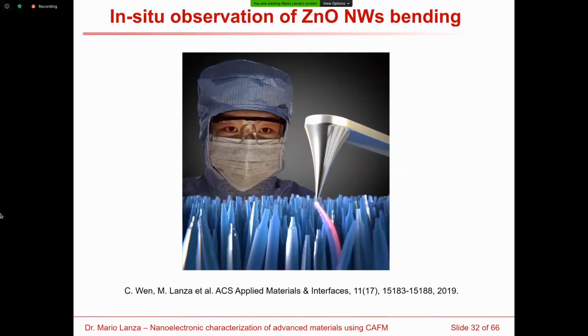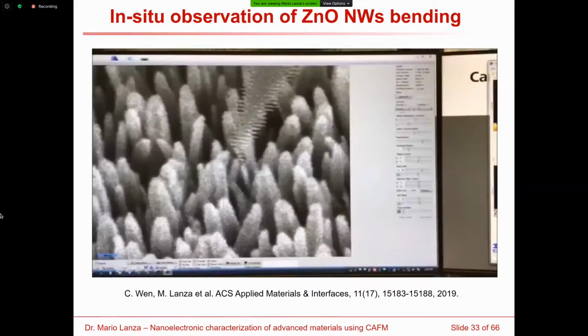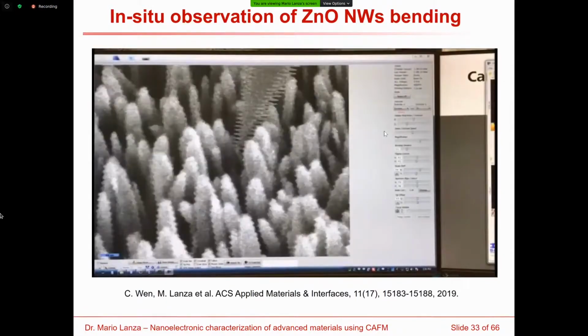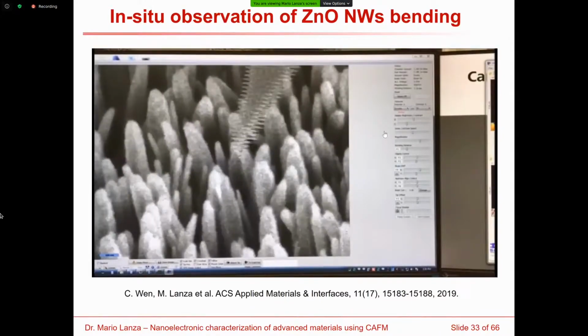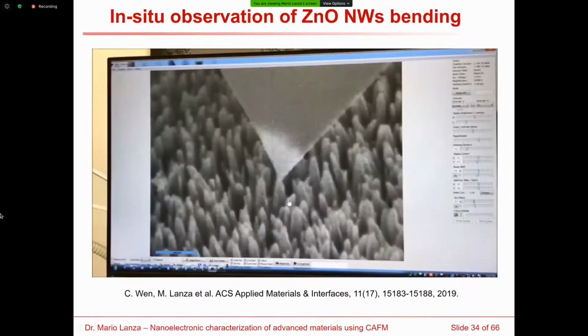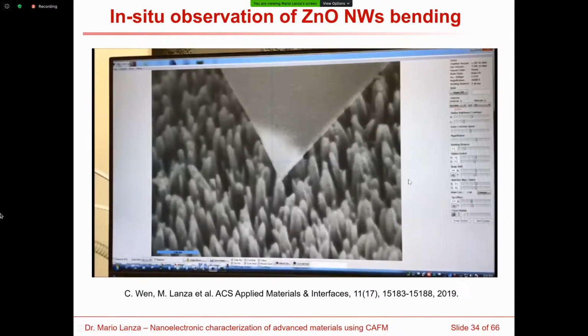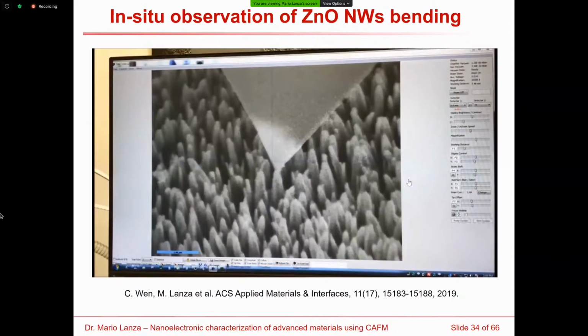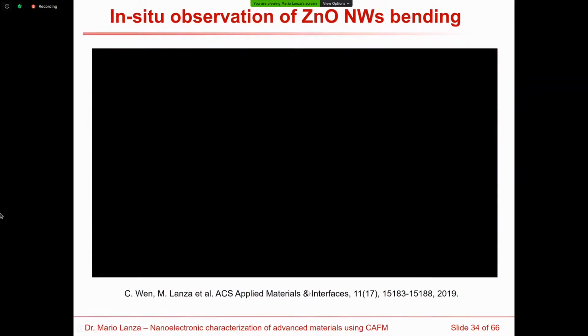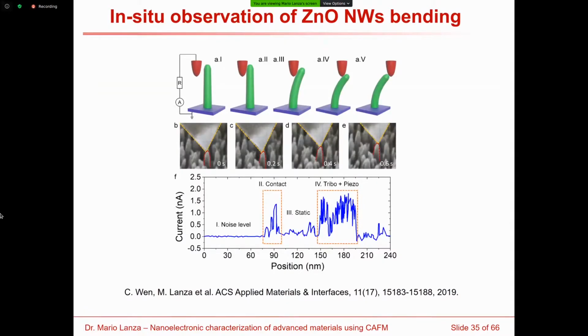And this is like if you were observing these current fluctuations in situ, and you can correlate them with the mechanical properties. So in this slide, I would like to show you one video of what you observe in the SEM when the tip is scanning the surface of the sample. You can clearly see how the tip is contacting the nanowires, and actually you can also put the tip on the nanowire that you want, and you can bend it intentionally by moving the tip of the conductive AFM. So actually, this allows us to correlate the mechanical bending of the nanowire with the electrical signals collected by the tip of the conductive AFM.